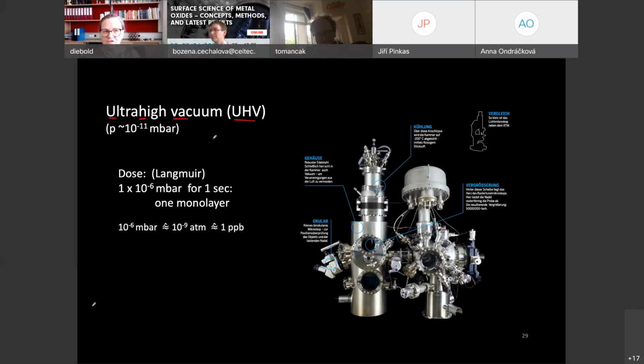So for ultrahigh vacuum surface science, we have this figure of merit. If you have a pressure of 10 to the minus 6 millibar, 1 atmosphere is 1 bar, so that's 10 to the minus 9 atmospheres, or 1 part per billion of some molecules in your vacuum or in air. If you expose it to a sample for 1 second, it's covered completely with 1 monolayer of dirt. So that's why we don't go to 10 to the minus 6 millibar, we go to 10 to the minus 11 millibar, because then we have 10 to the 5 seconds to do our experiments. So everything we do is in ultrahigh vacuum.